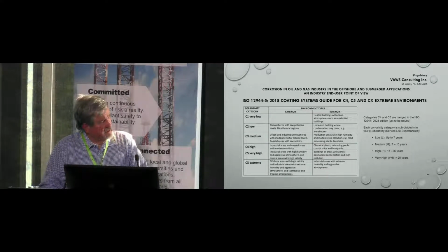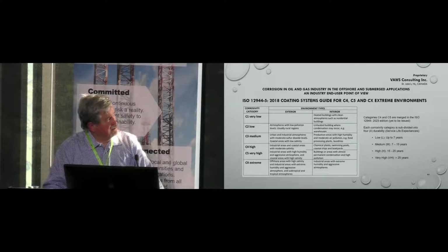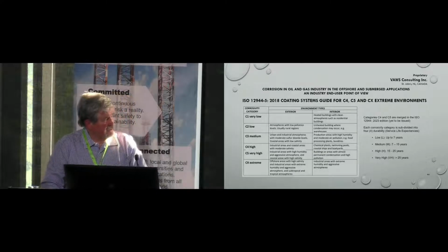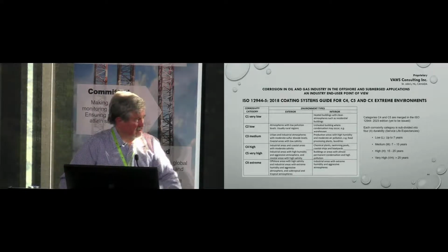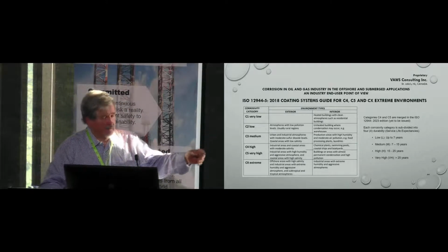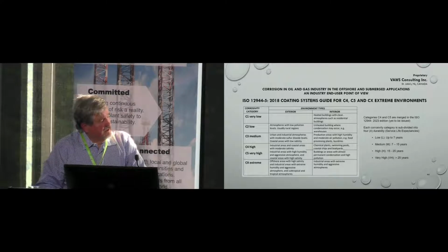What coating to use? There are a number of coatings you can use, and here is the ISO document, which probably is the best document we have for offshore application and onshore as well, which specifies the conditions C4, C5, and CX. The new version of this document, 2023, will have only one category, C5, and C4 will merge into it. For each category, there are nine sections in this document. They will tell you what coatings are the best, but that doesn't end the problem, because the problems we had in Sable Island were related to paint quality.